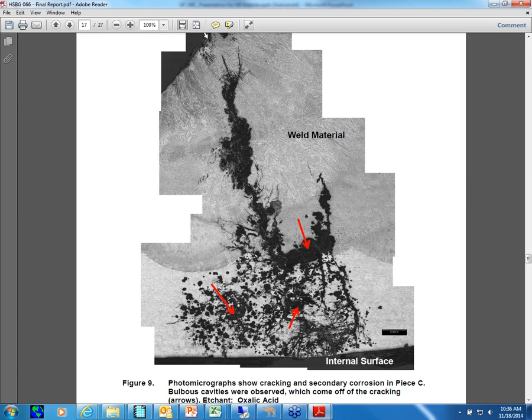So this is a 304 stainless steel spool piece, and generally you could say that thing's rated for a couple hundred parts per million of chlorides in a 100 to 150 degree environment. And so we're in a 13 ppm chloride environment with 150 degree hot water. We'd say, hey, we should be fine. We shouldn't expect to see any corrosion, but we do. That just goes to show how that microbe changed the conditions beneath its colony in such a manner that it would corrode the metal surface.